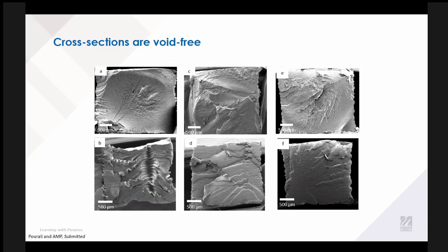And then in the failed specimens and the fracture surfaces, we're seeing that there's a lot of ribbon-like structure, which is highlighting just how much yielding there is, how much energy is being absorbed, before there's the final failure of these structures.